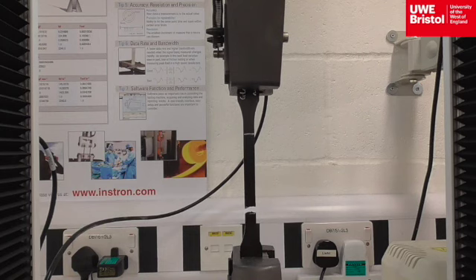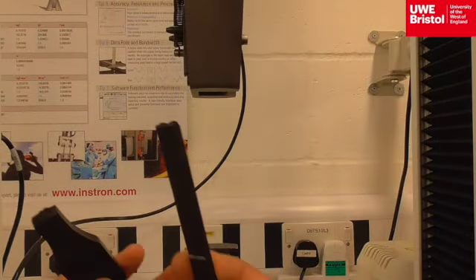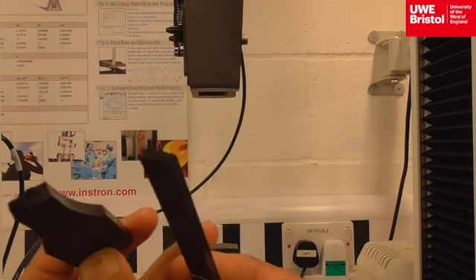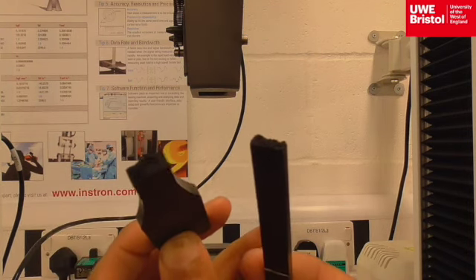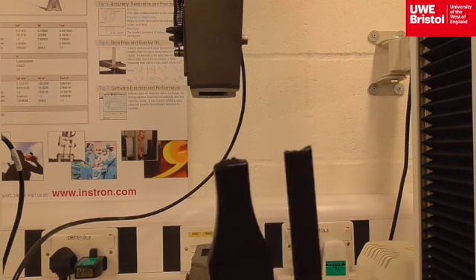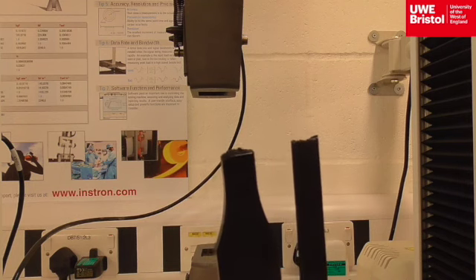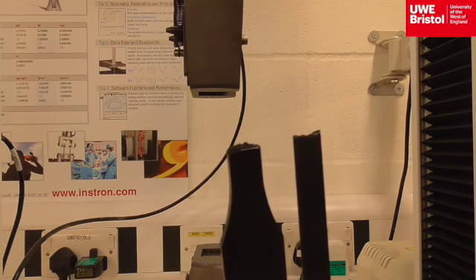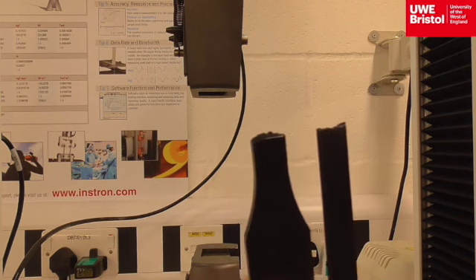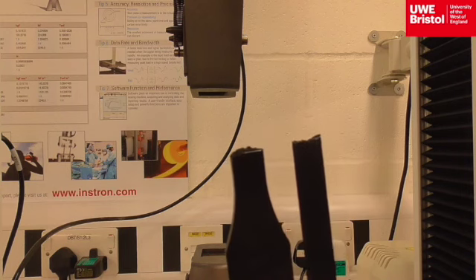And there is fracture. There is a small gap between the two halves, which indicates there is very little elasticity in the material. Having removed the specimen from the Instron, note the fractured ends of the glass-filled nylon. There will be protruding glass fibres at the face, it is very important not to place hands or fingers on those fractured faces.